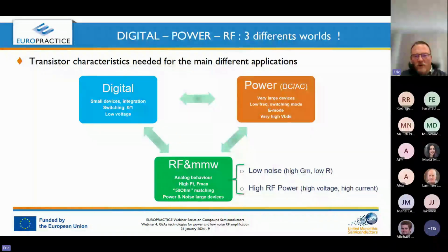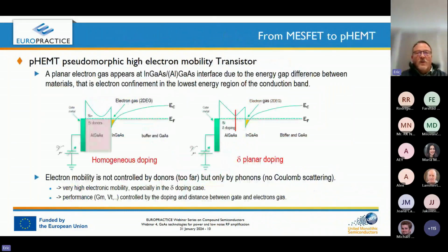So let's now be more focused on the III-V technologies. Why do we use in the III-V technologies the pHEMT, which is a pseudomorphic high-electron-mobility transistor, compared to the MESFET, which was, I would say, the initial device created 30 or 40 years ago on our technologies. In a pHEMT, we create through the gap difference between two materials, so, for example, between AlGaAs and InGaAs, due to the gap difference, when you build this epitaxy, then you create a gap, and in this position, you can create an electron gas,